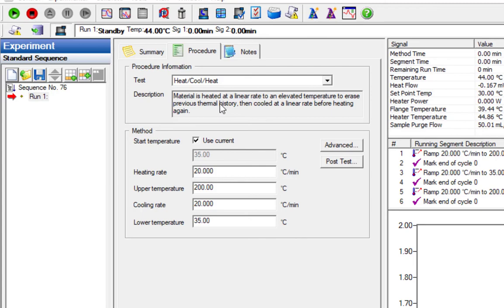Now, as I mentioned, we can go down to -90 degrees Celsius, but our starting temperature does not need to be below room temperature for this specific material. So you have to have a little bit of prior knowledge about your material before coming in and setting up the DSC. For one, we don't need to waste time. If the sample is already fully solidified at room temperature, we don't need to cool it. However, if the sample is liquid or is past its glass transition, then we would need to cool it. So you need to maybe look up some values, or if you can't find any information, then you'll just have to do a run to see. That takes a long time with a broad temperature range to see what range you actually need to confine it to for further runs.